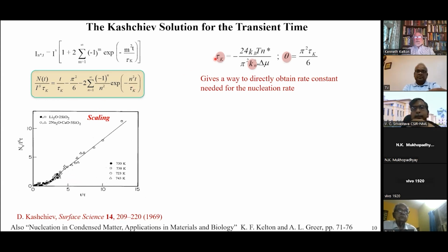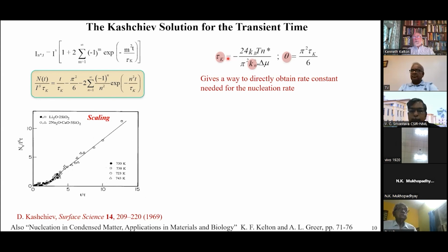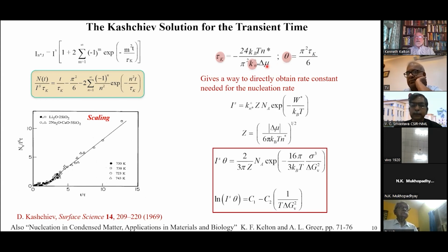Embedded in this is the induction time, or transient time, excuse me, which is related to the induction time by this simple expression. And he shows in his calculation that this transient time is given by this. I've highlighted the key factors. The transient time is related to the inverse of the forward rate constant, and it is directly related to theta. So that means I can use this measurement to calculate the induction time, or the forward rate constant.